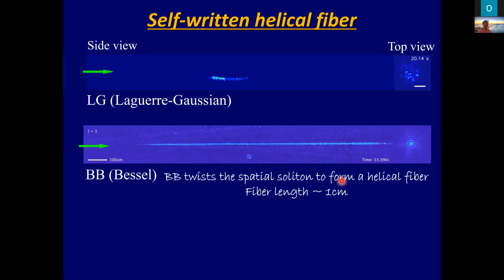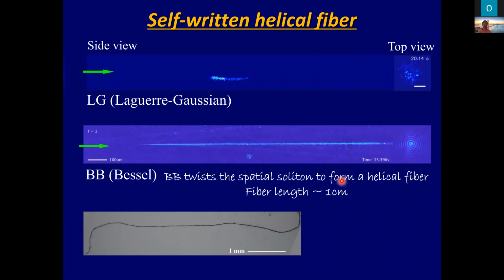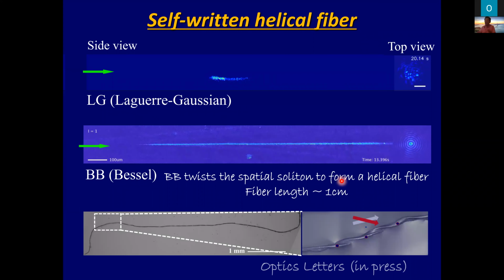So this is an optical image of the fabricated fiber. The length of the fiber is over 1 centimeter. The maximum size is about 2 centimeters or something like that. I want to show you a magnified image of the fiber. This fiber is twisted. The pitch of the twist is about 250 micrometers.